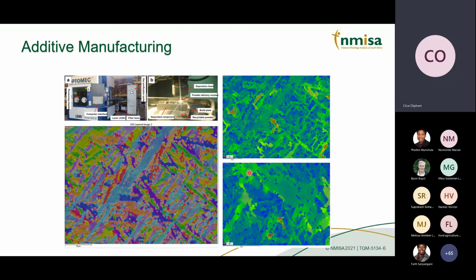On the right here, these two images basically show you the microstrain or the local misorientation map of a sample. This shows where there are perhaps some points where material failure can occur. These red spots are highly strained regions. Also, if you look closely in here, there's some discoloration in there. So from a product development point of view, that provides a wealth of information for industries to develop their advanced materials that they have made using additive manufacturing.